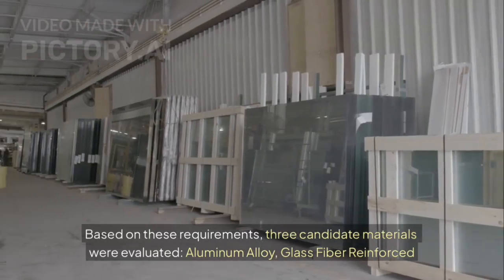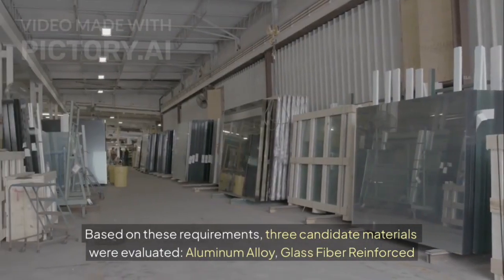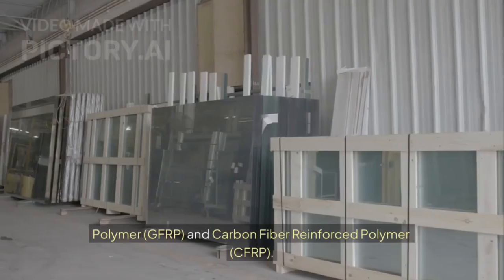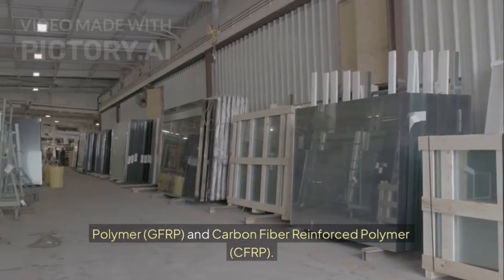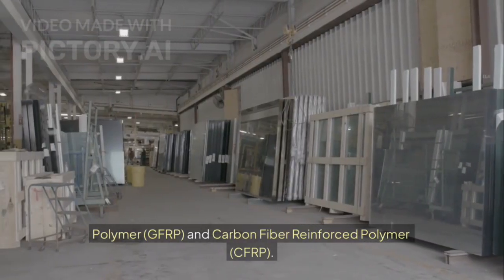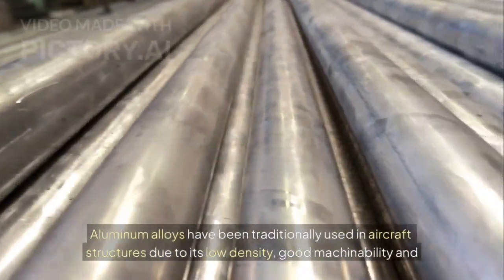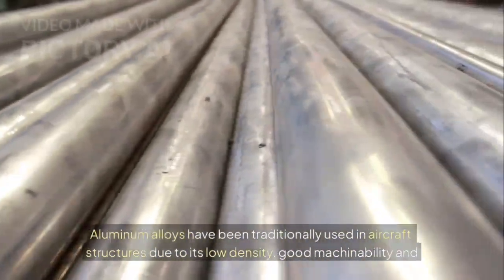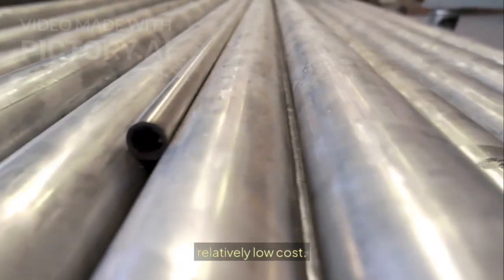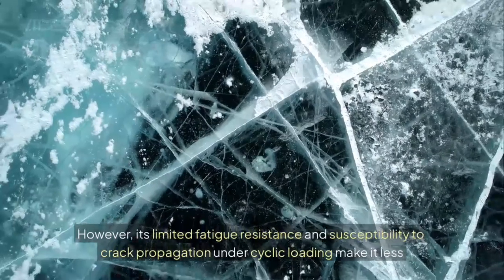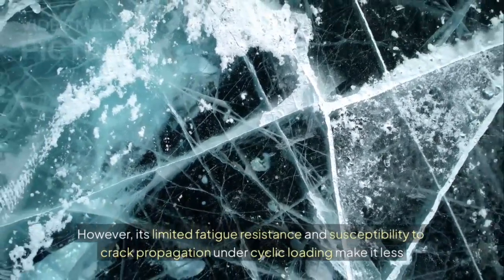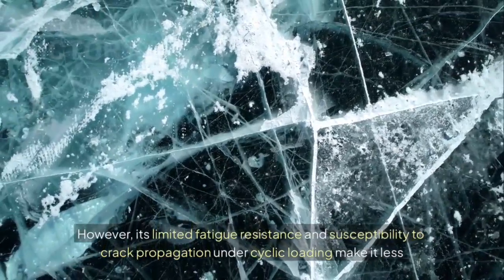Based on these requirements, 3 candidate materials were evaluated: aluminum alloy, glass fiber reinforced polymer, GFRP, and carbon fiber reinforced polymer, CFRP. Aluminum alloys have been traditionally used in aircraft structures due to its low density, good machinability and relatively low cost. However, its limited fatigue resistance and susceptibility to crack propagation under cyclic loading make it less suitable for